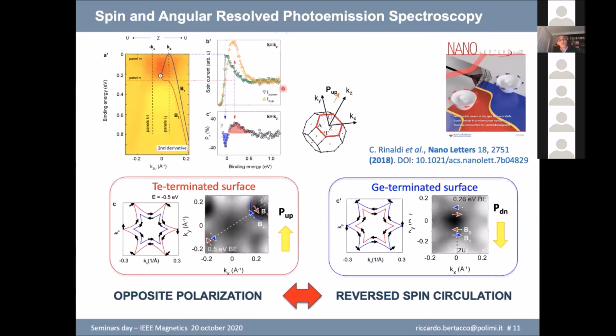But what is shown here is that looking now at the energy band dispersion here, you see that you have two different bands. One is blue, the other is red, and they should be associated to a different spin. This is exactly what you find in practice, because when you look now at the spectra for the two spin channels, you discover that these two points corresponding to these two peaks have different spin direction. This is exactly what you expect for a spin-momentum locking. The spin is perpendicular to the momentum, and in the two Rashba bands you have opposite spin. As you can see here, this is the estimated polarization. So looking now at the spin texture, this means that for a tellurium terminated surface with the polarization upwards, you see that the sense of circulation of the spin is clockwise in the outer band and counterclockwise in the inner one.